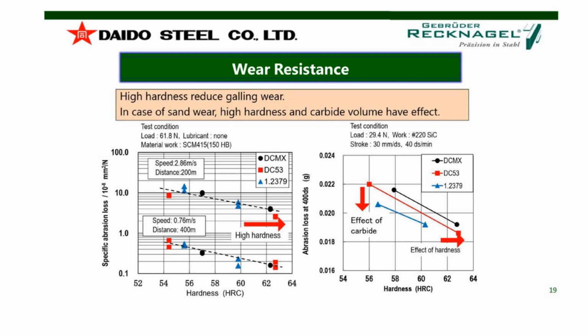And of course, also in case of galling, if you have a problem with galling, the space between the single carbides is very important. If you have a big space between the carbide linings, like you have with D2 grade, you have a big problem with galling. And if you have smaller linings or very small space between the single carbides, you have fewer problems with galling. And the situation with DCMX is absolutely better than with D2 grade for galling. Yeah. Let's go forward.